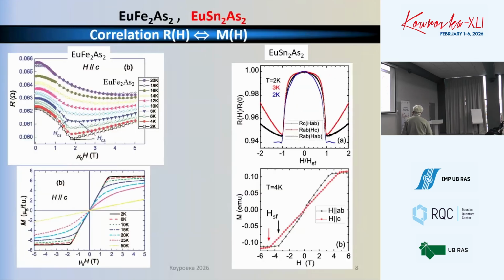And what is remarkable about this feature? When we study the magnetization, it seems to be quite typical. All of these materials, like europium iron two arsenic two and europium tin two arsenic two, exhibit a very simple magnetization curve just from the textbook. It develops linearly until you fully polarize spin. And one can see that the spin polarization field slightly depends on the orientation. If the magnetic field is applied in plane, then it is easily magnetized, or when you apply the magnetic field perpendicular to the basal plane, then the magnetization is achieved at a little bit higher fields.